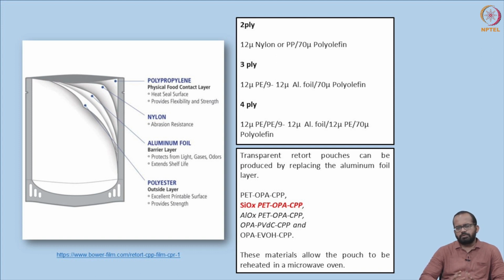And there are also two types of retort pouches: transparent retort pouches and opaque retort pouches. Opaque retort pouches are usually made with aluminum foil inside. Transparent retort pouches can be produced by replacing the aluminum foil layer with silicon dioxide or a similar transparent material, which has the same barrier properties as aluminum. But in the case of opaque retort pouches where aluminum is present, the consumer cannot directly put the pouch inside a microwave oven for heating. But in the case of see-through pouches, since they have silicon dioxide and other similar materials instead of aluminum foil, they can be directly heated after opening in a standard microwave.